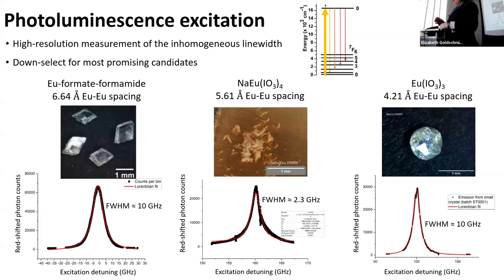So then we started to think, is there a material with a synthesis method in the literature, but with a different rare earth instead of europium, and we think it should work if we just swap the rare earths because they're very similar. We also did some DFT to identify whether this compound would be stable. For that, we looked for things likely to have a big nearest neighbor spacing given the crystal structure. We also want the other elements in there to be monoisotopic, with only one naturally occurring isotope, because that also helps with the inhomogeneous broadening. Having multiple isotopes is a source of defects as well, the wrong isotope.